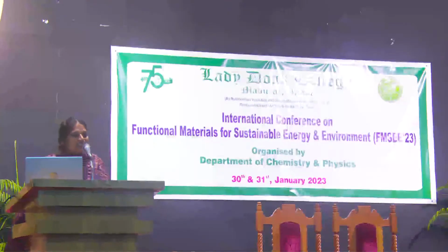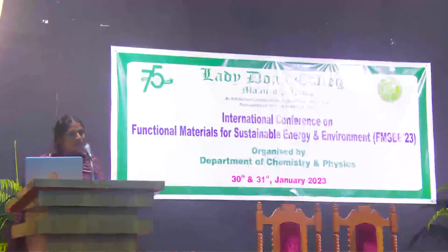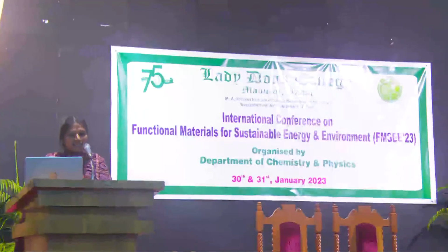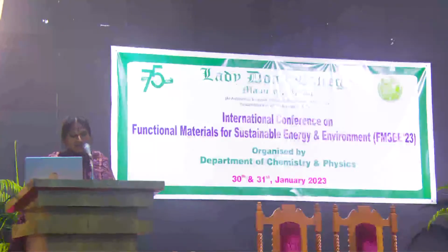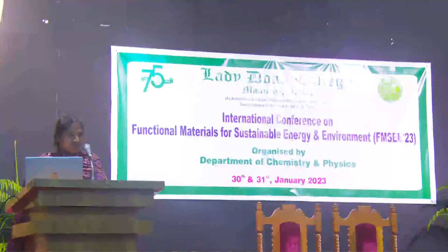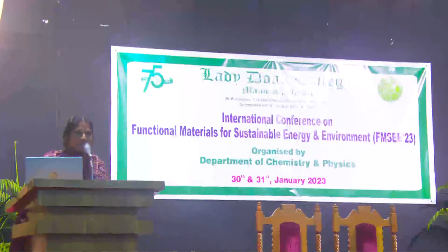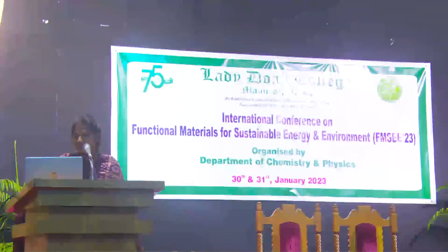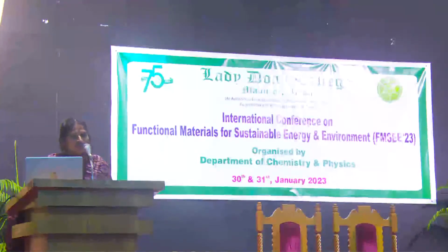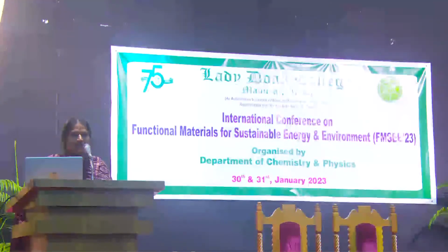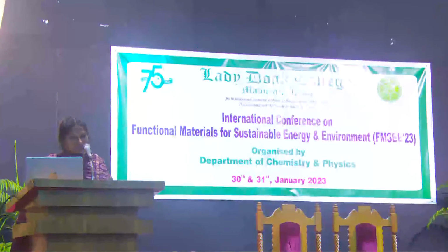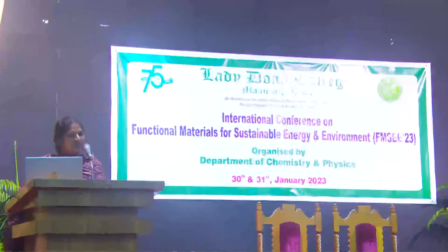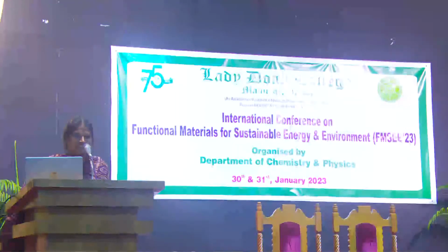And in results and discussion, XRD and Raman confirm the formation of amorphous carbon, and these peaks confirm the amorphous nature of the prepared material. The ID/IG ratio of the prepared sample is 0.85, so it has defective sites on the surface. And the SEM image confirms the formation of pores on the surface. These pores will help ion transportation during electrochemical interaction. EDS also confirms the presence of only carbon and oxygen. No other element traces are noted, so it confirms purely activated carbon.